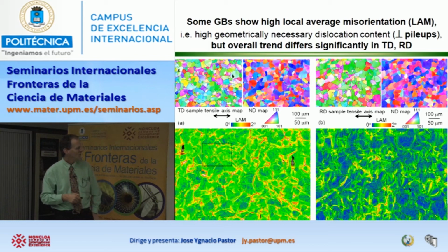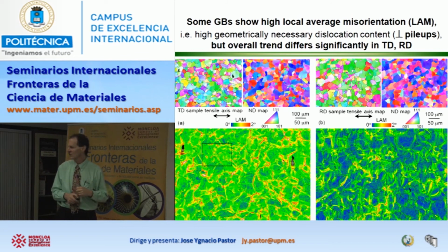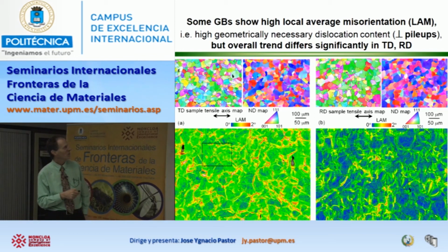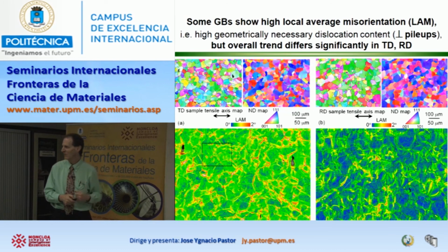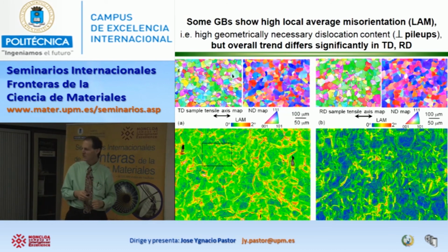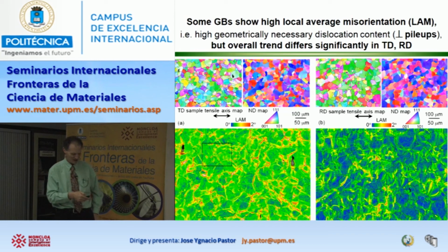But what you note here is that along some of the grain boundaries, but not all of them, it got sort of red. That means right against the grain boundary, there's a bigger change in local orientation gradient than there is in the grain interior. So basically, what we're looking for are regions that have high geometrically necessary dislocation content, or in other words, dislocation pileups right against the grain boundary, which cause a bend in the crystal right next to the boundary. And we can detect that in the regions that are red. You can see that many of the boundaries here are not red, but some of them are.